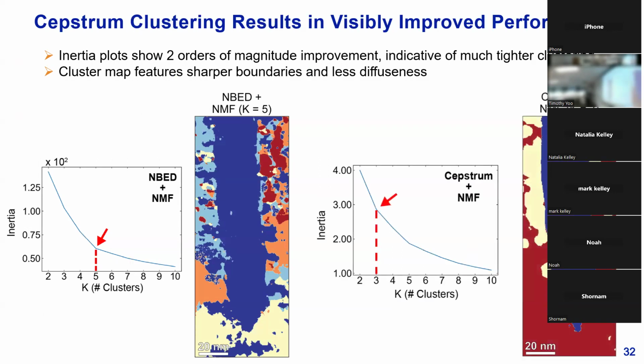And right away, here's the result on using Cepstrum patterns. From the inertia plot alone, we can see that these values are about 2 orders of magnitude lower, already indicating a much better clustering result. And we can also see that in the map itself, there are nice sharper boundaries around particularly this precipitate one. And we see less of that diffuseness that we see on the left side.